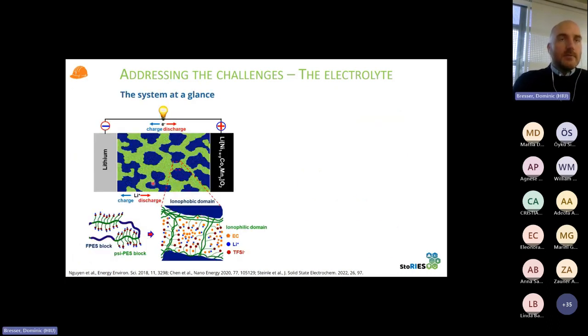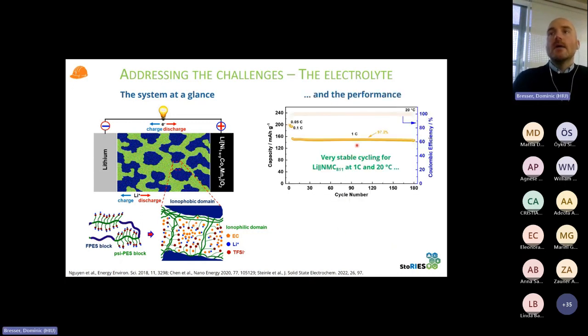And this is here the system at a glance, basically. So let's assume we have a lithium metal electrode here, right, and the lithium nickel cobalt manganese oxide here at the positive electrode. And then in green here is the ionophilic domain. So these block copolymers tend to separate into domains, ionophilic here in green and ionophobic here in blue, which, as said, gives us the right combination of mechanical properties and electrochemical properties. And then you can see here in this magnification, basically the preferred coordination of the lithium, of the ionophilic domains, and specifically apparently the lithium cations, by these solvent molecules. Here EC, so ethylene carbonate, but as said, anything with a high dielectric constant works well, basically. And then with these systems, we can get very stable cycling, right, at a rather high C rate of 1C.